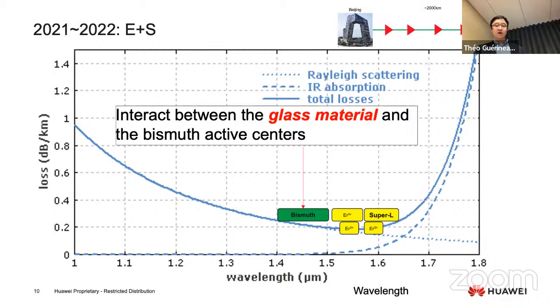So here we have a collaboration with Professor Younes, and we are working on developing the glass materials, glass fibers that can make the best use of the spectroscopic property of bismuth active centers. And this is in fact very tricky. Bismuth is not as stable as erbium. It can be affected by many factors, like the temperature, the gas flow, the drawing speed, everything. It's a very challenging work, but we have shown very encouraging results until now.